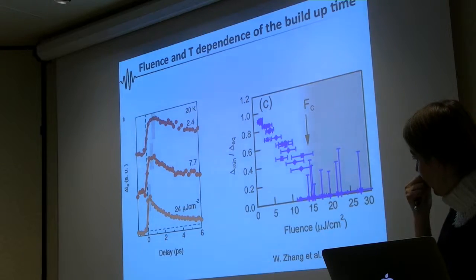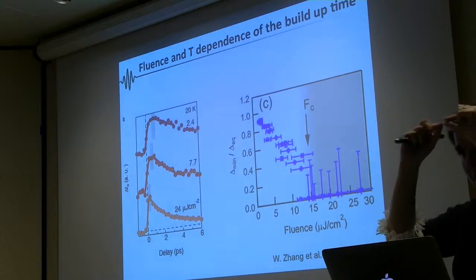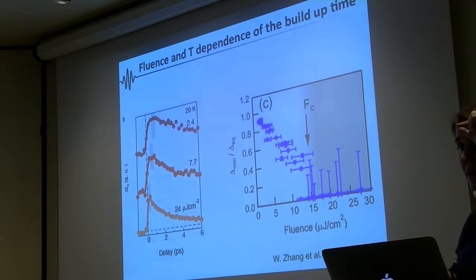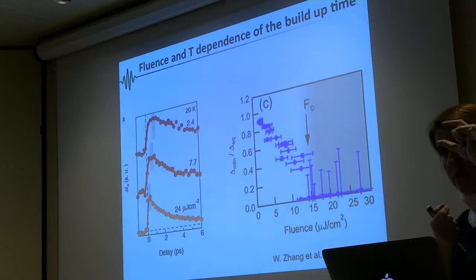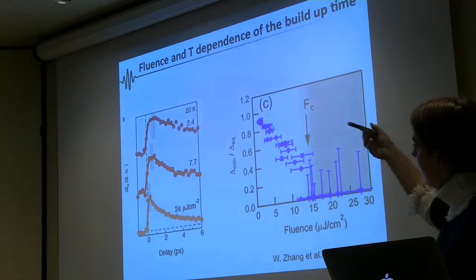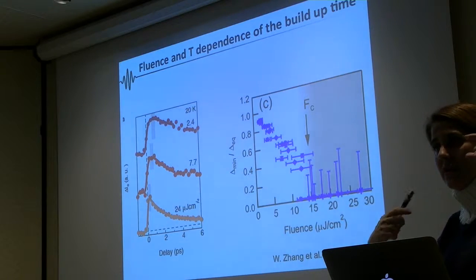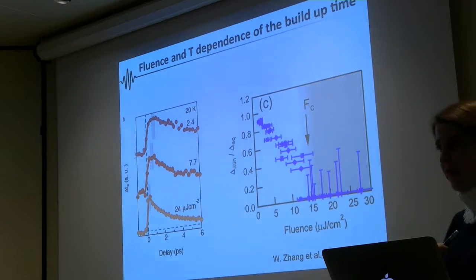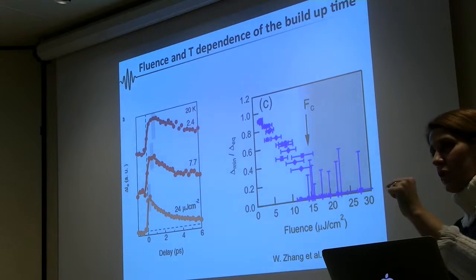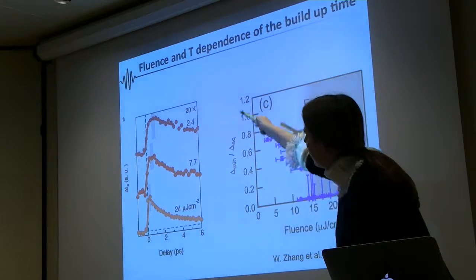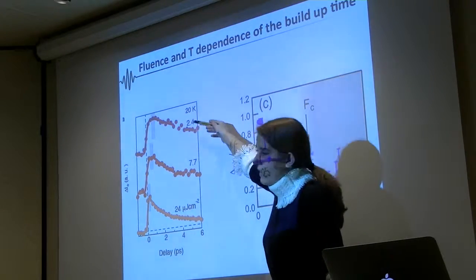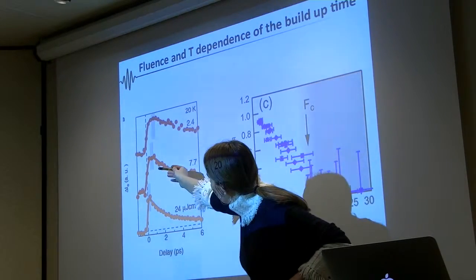So then the next thing you can do, you can say, well, what if I sit in that particular point? So I am in a superconducting state where I have a gap, I'm sitting inside the gap, I do my experiment, but now I'm changing the fluence. So I'm changing the amount of energy I'm delivering to the system. And I showed you before that depending on how much energy you give to the system, you can not affect the gap at all, close partially the gap, or completely close the gap. So this is summarized here. You see that if you are in a regime where you are closing the gap by like 60%, then you see that there is a delay in the response. So the system doesn't respond right away.